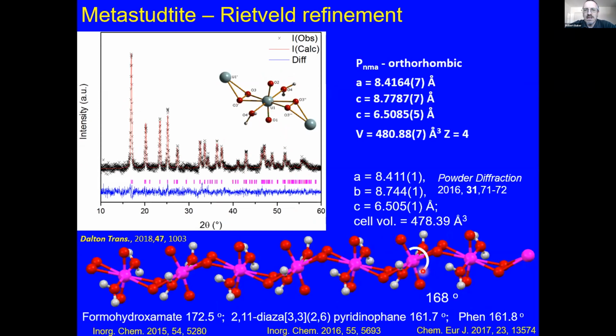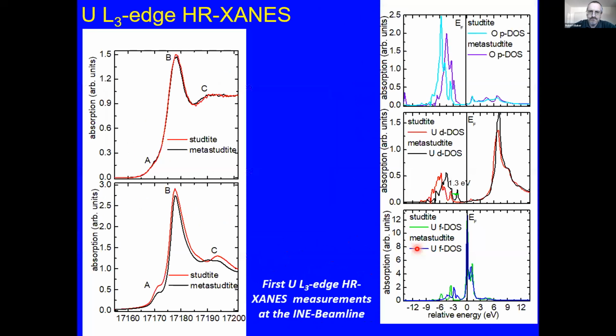Now, of course, you shouldn't put all your eggs in one spectroscopic basket or structural basket. So we've tried to look at this in more detail because this is really quite unusual. But before we get to that, here are the high resolution XANES spectroscopy that we measured at ANKA quite a few years ago now. So there are 3 features: this pre-edge feature, the main feature, and then this post-edge feature here. And fitting this data using FEFF calculations, we can get to the density of states plots.